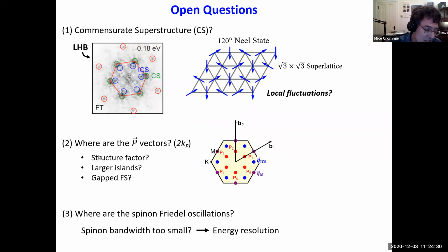But there are some possibilities. For example, there could be a structure factor argument that causes them to have much lower amplitude. Another possibility is that these are longer wavelength features. And to see these longer wavelength features, because the K value is smaller, we need larger islands. So it might be just that our islands are not large enough yet to see the P vectors. And so we're still looking for those.